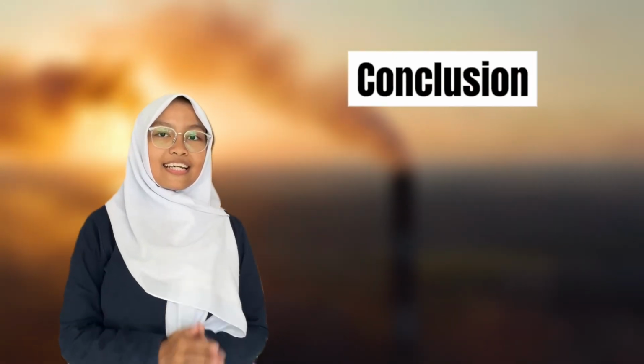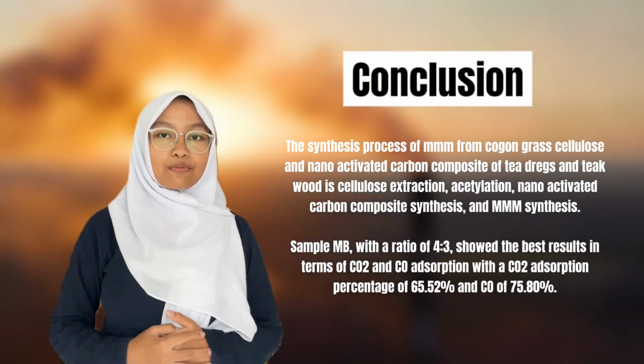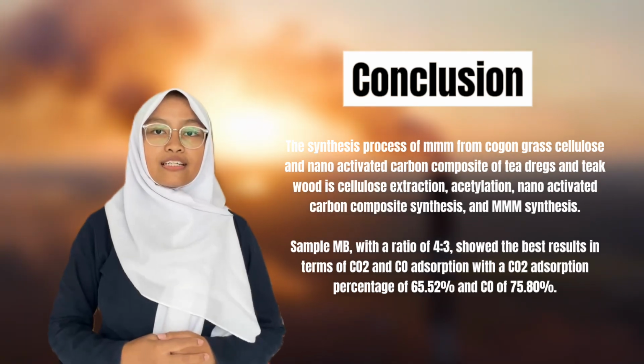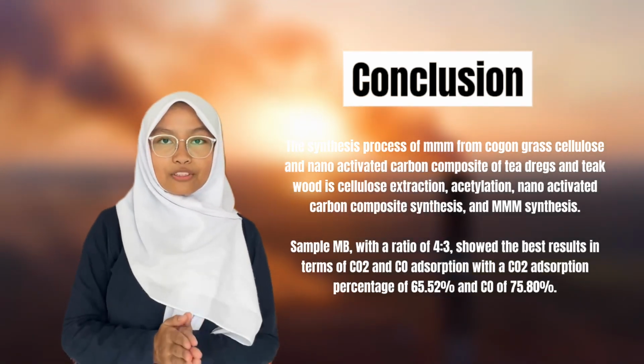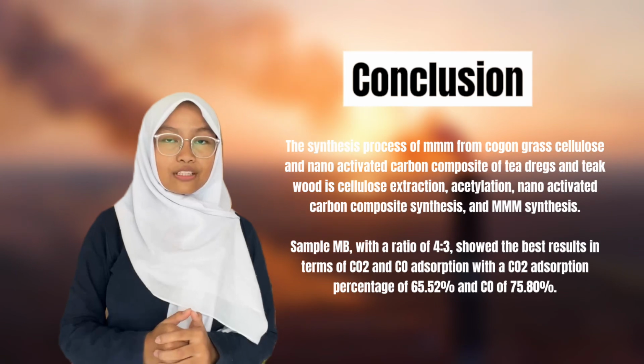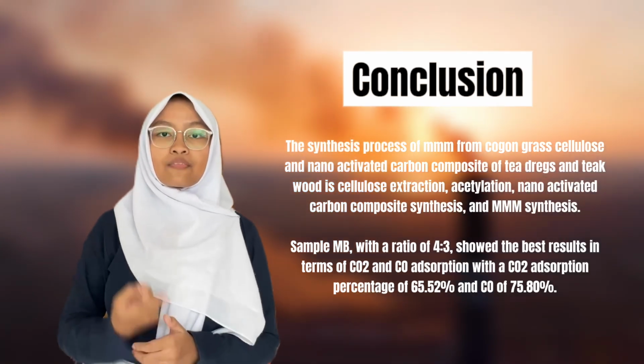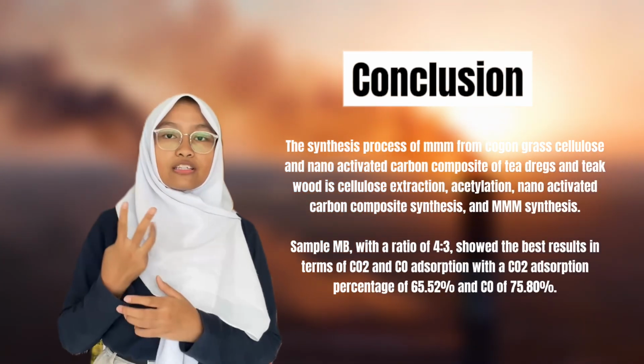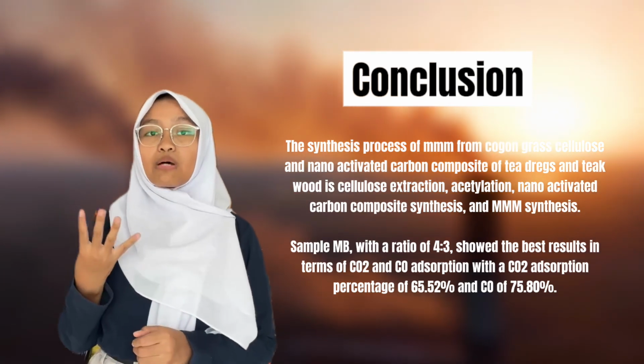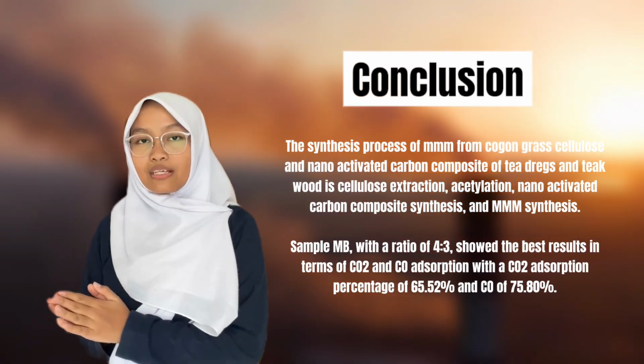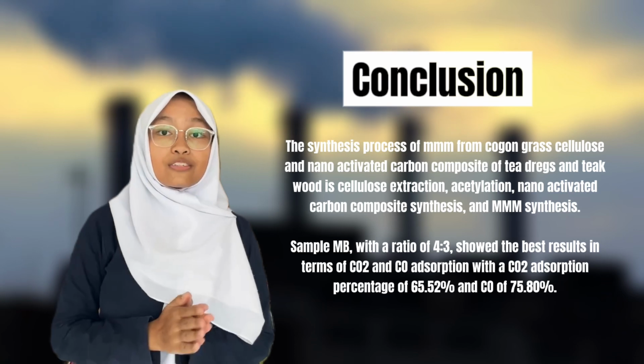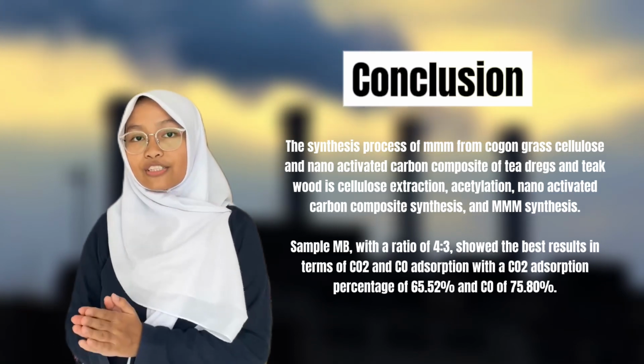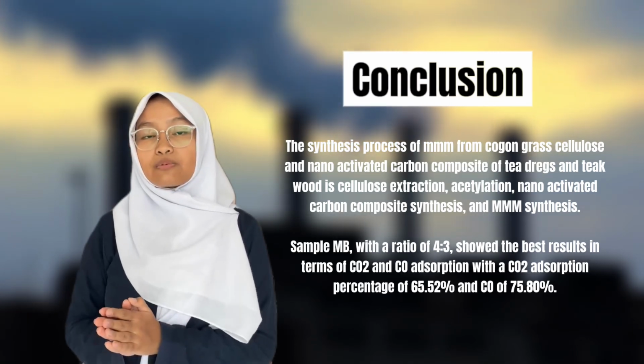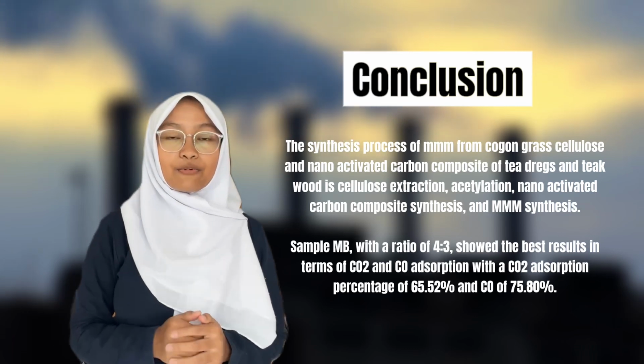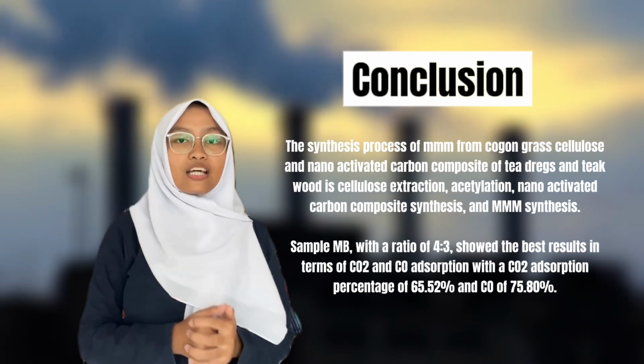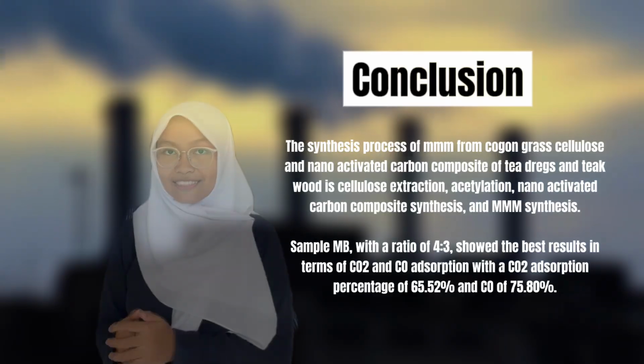So, from this study, it can be concluded that the synthesis process of MMM from cogon grass cellulose and nano activated carbon composite of tea dregs and teak wood is cellulose extraction, acetylation, nano activated carbon composite synthesis, and MMM synthesis. Sample MB with a ratio of 4:3 showed the best results in terms of CO2 and CO absorption, with a CO2 absorption percentage of 65.52% and CO of 75.80%.